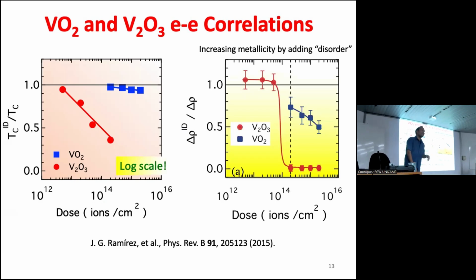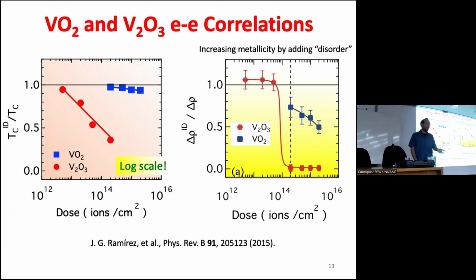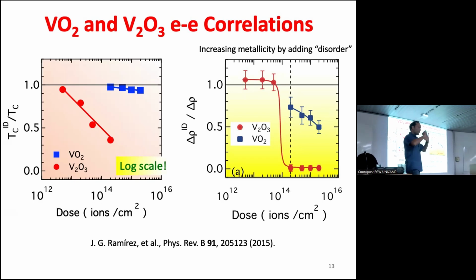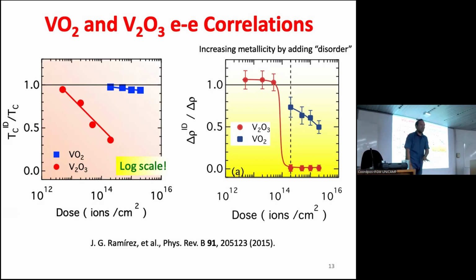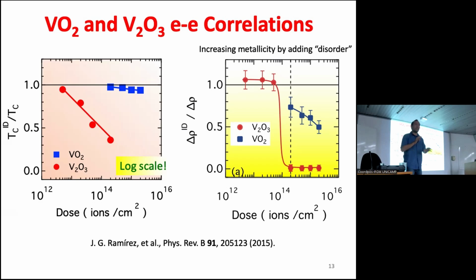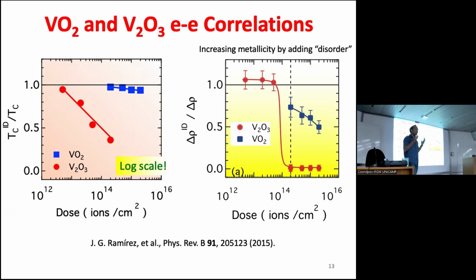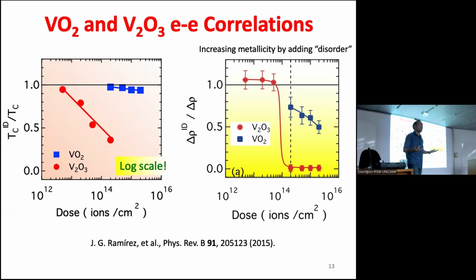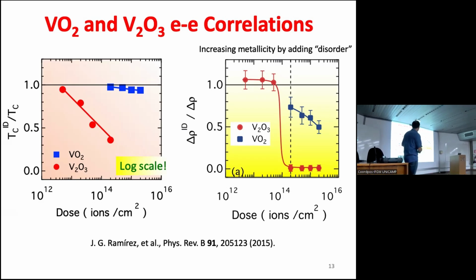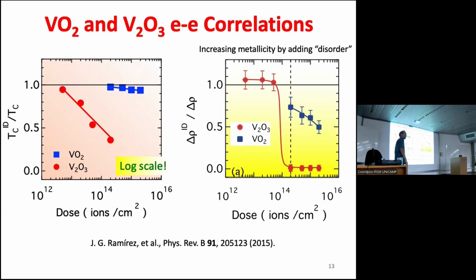If I look at the change in the resistance before the radiation and after the radiation, what is to me most amazing is that the resistance of the material, both VO₂ and V₂O₃, gets better. So you have a material that you disorder, and somehow it becomes more metallic. If you think about what a metal is, that doesn't make sense, right? If you disorder something, it becomes more metallic. But that happens. It happens even more in V₂O₃. So it makes sense with what I showed just before, the degree of correlation between VO₂ and V₂O₃.